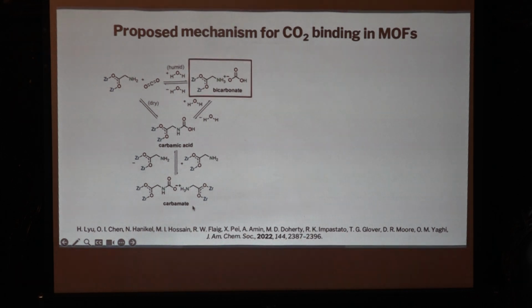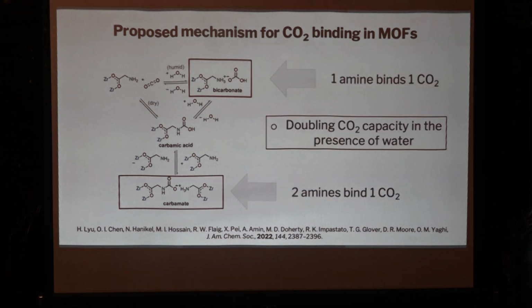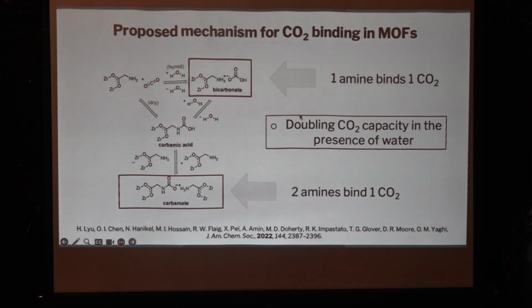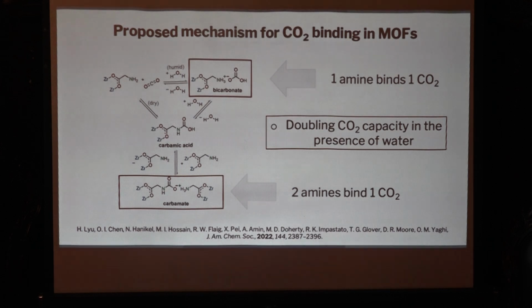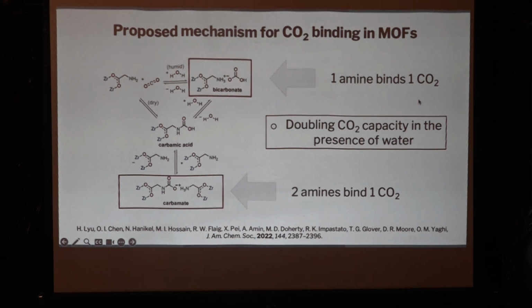Now, in the presence of water, you have the ratio of one amine binds one CO2, while in the absence of water, two amines for each CO2. So what I want to say is that this discovery that we can double the CO2 capacity in the presence of water, which is always present in combustion gas or in the air, means that we can have a 1-to-1 ratio between the amines that we functionalize the pores with and the CO2.